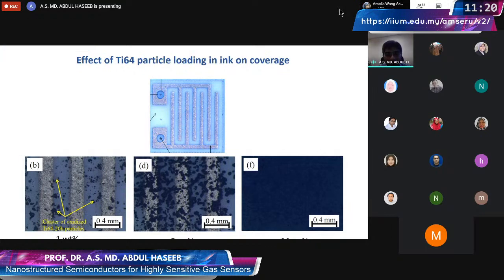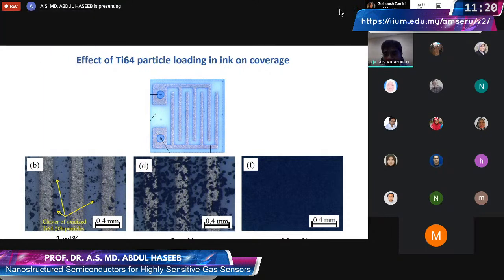And we have done the test, and we have seen that in our case, between 2 to 5% loading, we could get a structure where we have some kind of conduction path at different places. And that is good enough to give us a consistent signal. If we go beyond this, then we create a very thick layer, and they would short circuit the whole thing. The resistance is very low, and they do not change in response to the gases. So this appears to be good in our case. Did I answer your question?